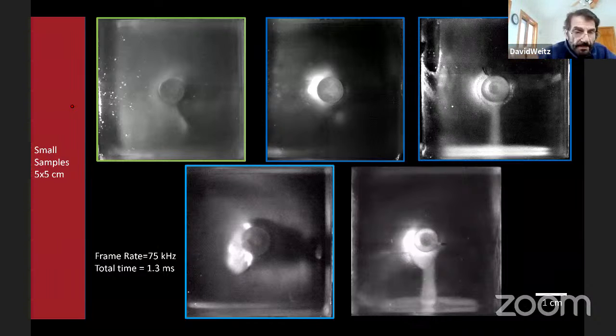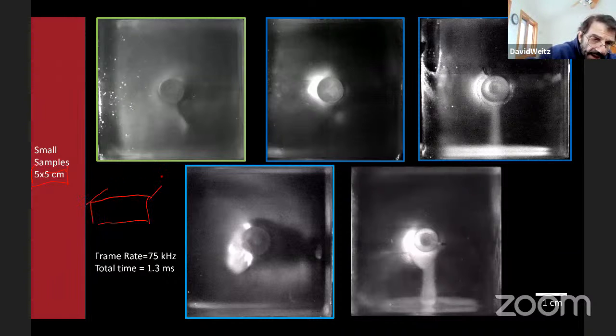This particular sample is a 5 by 5 square. These are each of these, actually, these are 5 samples. I'm going to draw here just so that it's more clear. It's something that looks like this. And so this is 5, this is 5. It's thinner this way. And in the middle, we've drilled a little hole and we inject fluid in the middle, and we're looking from the bottom. So you're looking up, and this is where the fluid is going to come.